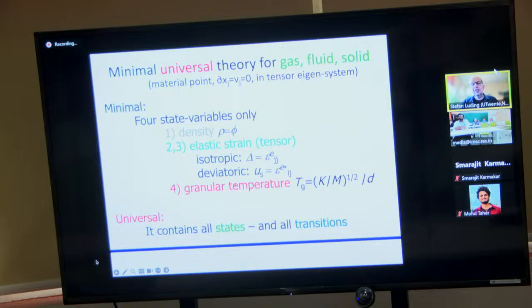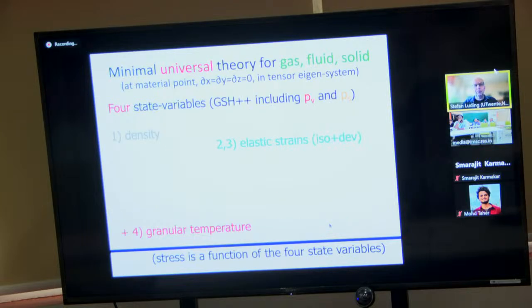Number 4 is the temperature or the granular temperature. If you really want to make your life complicated, then you have granular temperature and temperature, both. But this is not needed for powder systems and particle systems, so I stopped with the granular temperature. The granular temperature is the fluctuation kinetic energy divided by mass, which gives us a velocity, and velocity divided by diameter gives us a time scale, a rate. So granular temperature in this definition is a rate, a 1 per time quantity, and that one will show up in all rate-dependent phenomena. I call it universal because it contains all states and all transitions, at least all those which I could come up with. Maybe there are more.